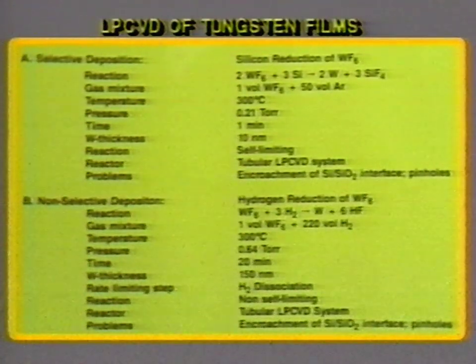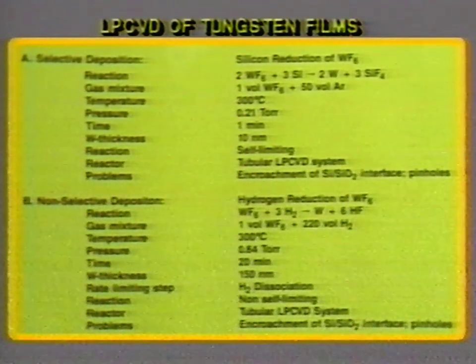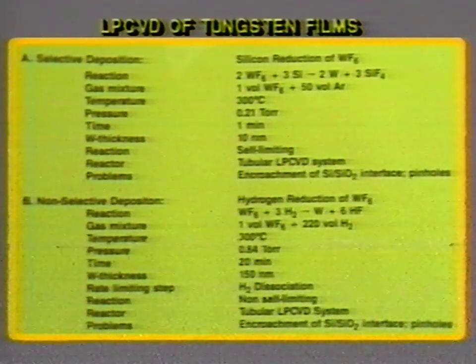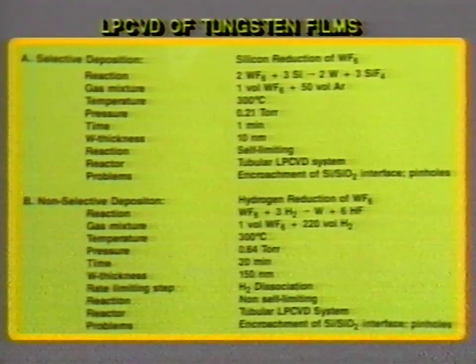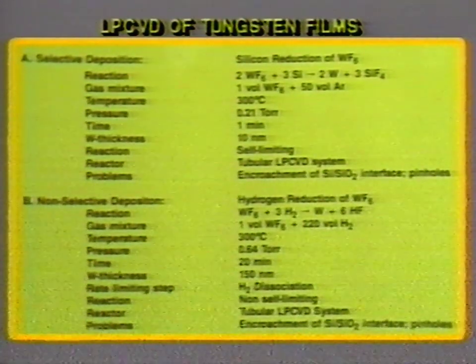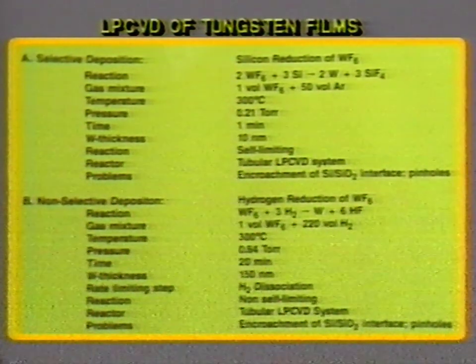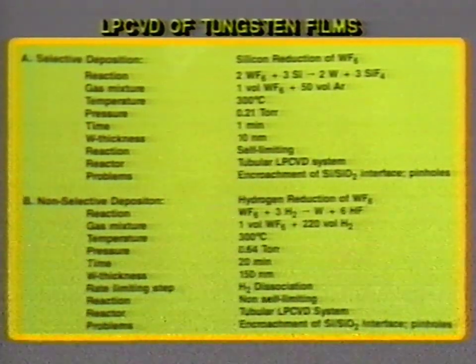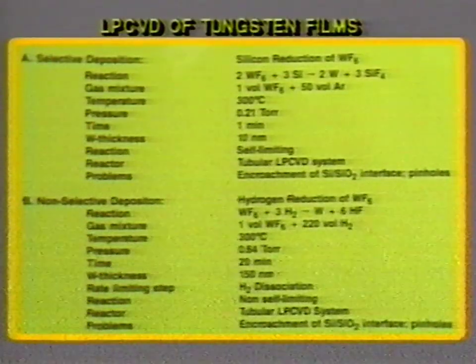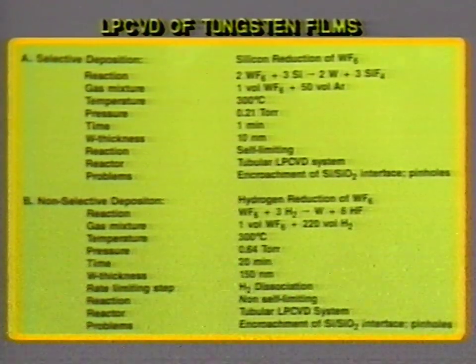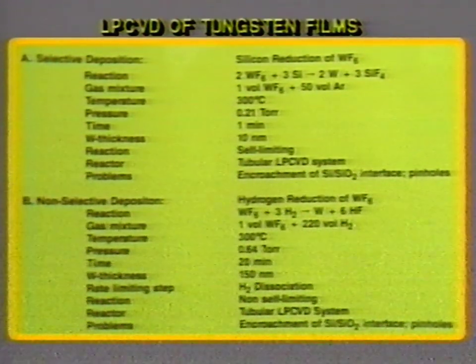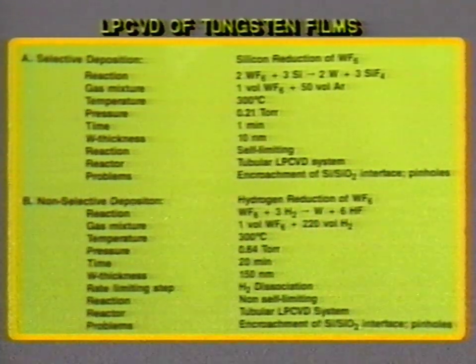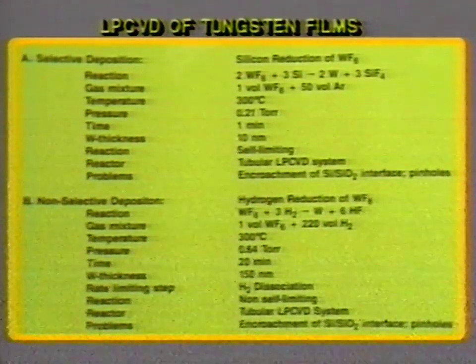Which of course may be desirable later on if we do want a continuous film that is non-selective. But if we want selective deposition, we have to be very careful with the temperature, with the dilution, with the rate of deposition, and all the finer points in the CVD reaction to produce films that are confined to a particular area. Now the thickness is limited to about 100 to 150 angstroms of tungsten, as indicated here, because after that there is no more silicon available for the reduction of the tungsten hexafluoride. So you will finish the reaction itself at that point.